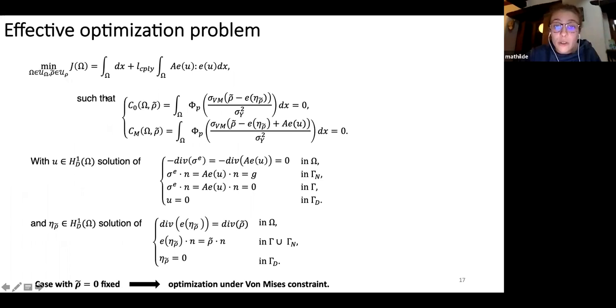But we see here that we don't have rho anymore. We have the projection of rho onto the space of self-equilibrated stresses. So here and here we have the projection. And so now we characterize the displacement U with the same linear elasticity equation. And then this eta that is involved in the projection is computed through this partial differential equation. And then we can optimize the same way. And we can notice that if we fix the tilde rho to 0 and we don't optimize it, we actually go back to the optimization problem I was presenting in the first part with no plastification allowed.